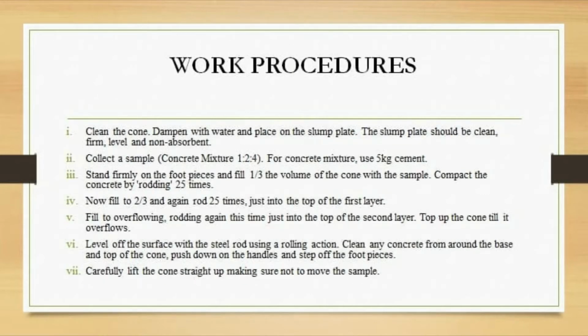Work procedures. First, we need to clean the cone. Dampen with water and place on the slump plate. The slump plate should be clean, firm, level, and non-absorbent. Second, collect a sample. For the concrete mixture, use 5 kg cement. Third, stand firmly on the foot pieces and fill 1/3 the volume of the cone with the sample. Compact the concrete by rodding 25 times. Fourth, now fill 2/3 and again rod 25 times just into the top of the first layer. Fifth, fill to overflowing, rodding again, this time just into the top of the second layer.